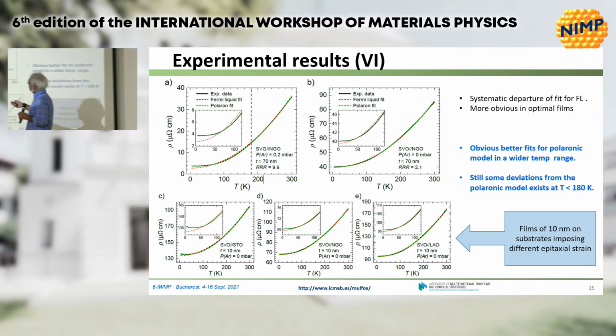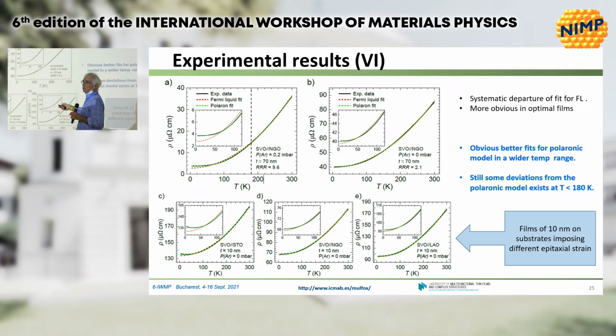The red points are the fitting that I showed you before, the T-square standard electron-electron correlation plot. And now you see the dotted points on top of the experimental data, the green points, and you cannot even distinguish them at this scale.